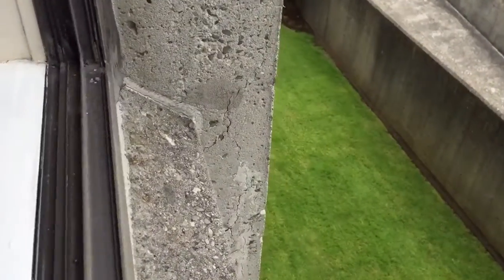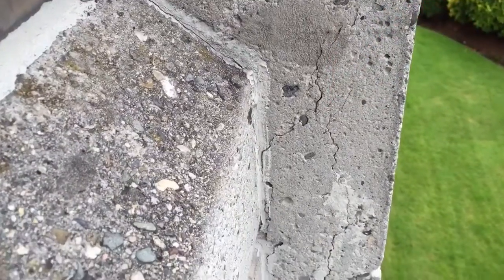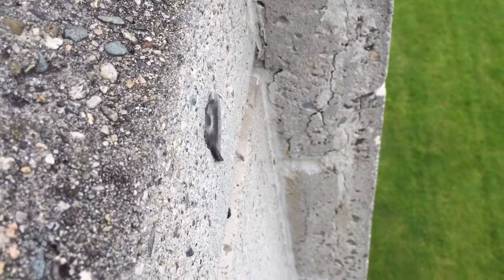So when I was doing the exterior inspection of this building, I noticed numerous cracks in the structural concrete, much like this one. If you look down a little bit further, you'll notice that the concrete continues to crack and a lot lower, you'll notice a piece of steel. That piece of steel is a structural rebar that was actually cast in the concrete when the concrete building was built. When that rebar starts to show signs of deterioration in the way of rust, the rust expands the steel and it pushes the structural concrete off the building, causing serious problems.